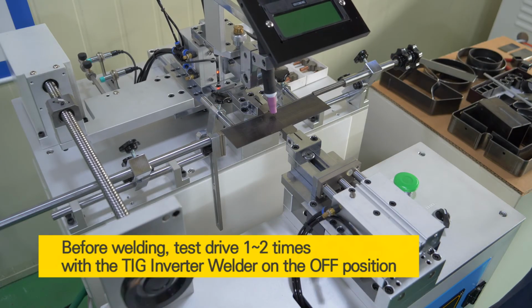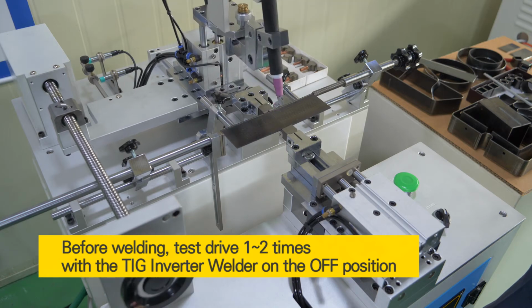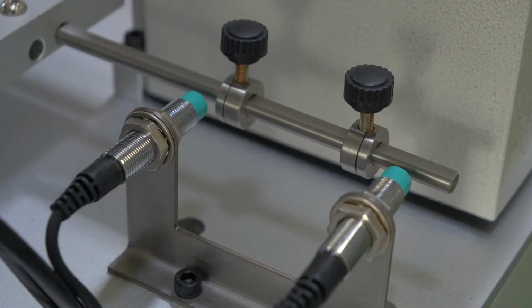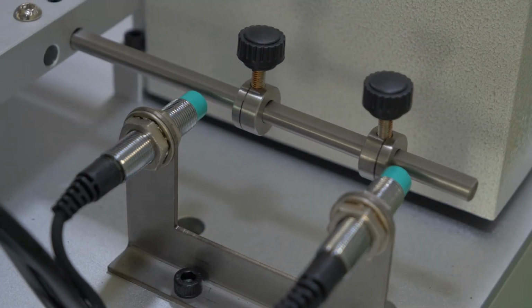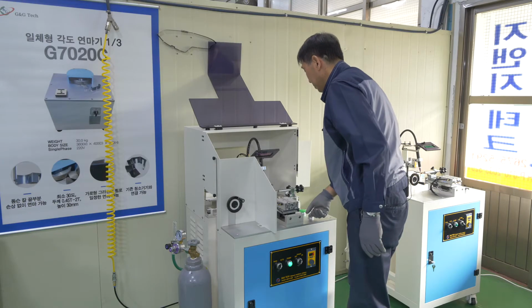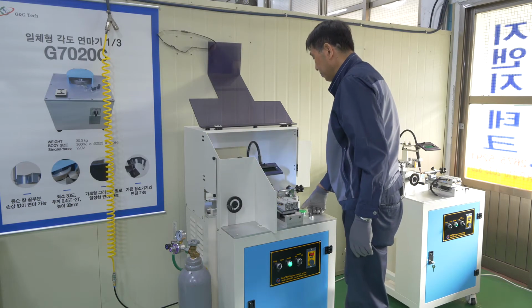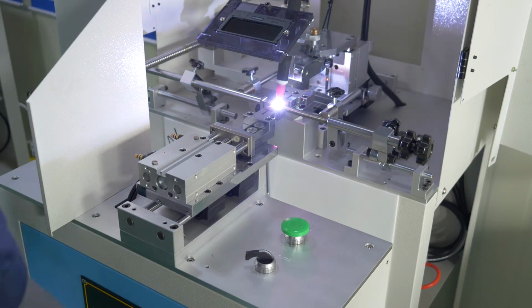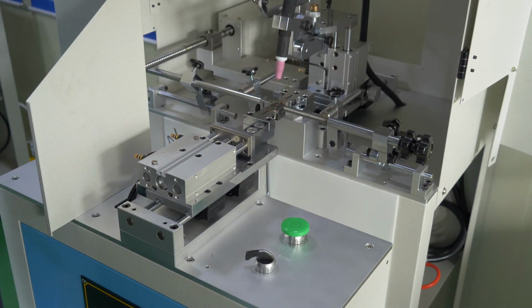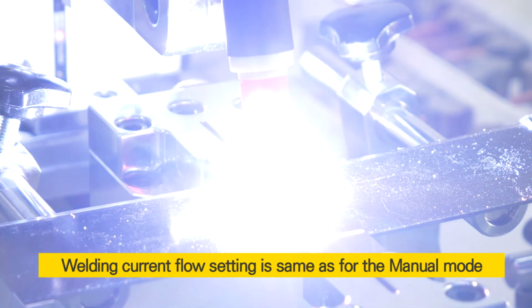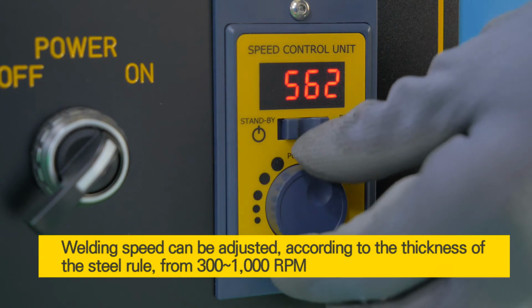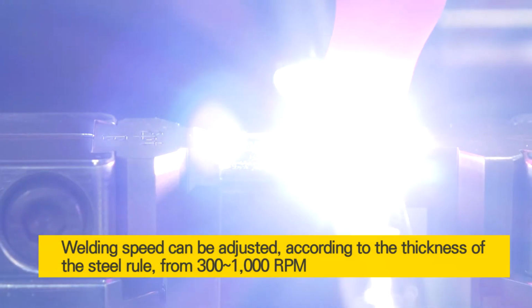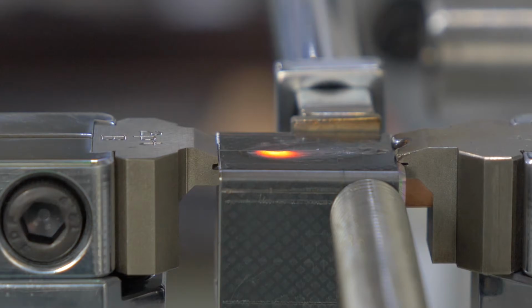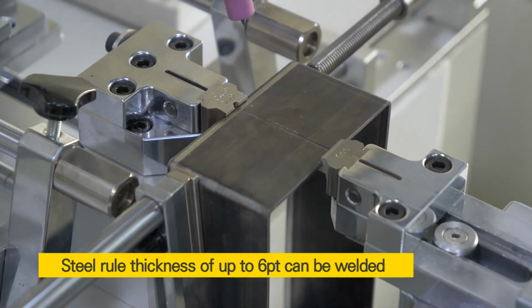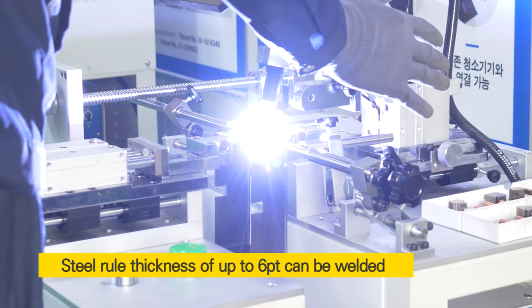Leave the power switch of the TIG inverter welder on the off position and test drive 1 to 2 times to ensure proper operation of the welding range. Switch the power of the TIG inverter welder to the on position and push the start button to perform the automatic welding. Set the welding current flow according to the thickness of the steel rule and adjust the speed to get the desired welding quality. Steel rule thickness of up to 6 pt can be welded.